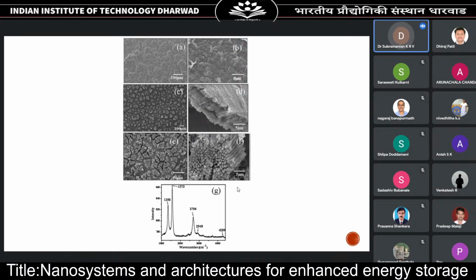Initially the conducting polymer was electropolymerized, right? So what you do is you take polypyrrole, which is the conducting polymer, and then we electropolymerize it onto a substrate using applied voltage, right? And you can see the polymeric nanotubules in part F of the figure. On top of that, we have deposited the graphene by electrophoretic deposition. So you can see C and E, that is the combined structure of the graphene and the polypyrrole, right? These are all very, very tiny structures. And the graphene that we deposited had a distinct Raman signature as shown by the graph below.